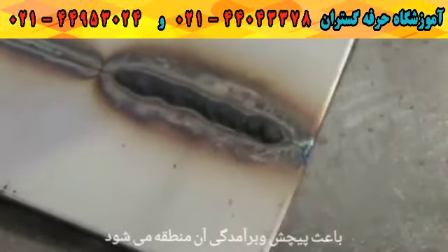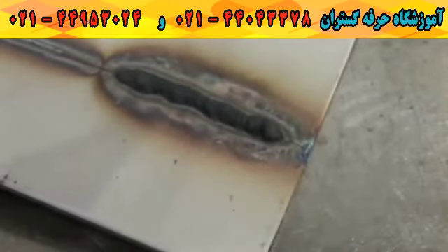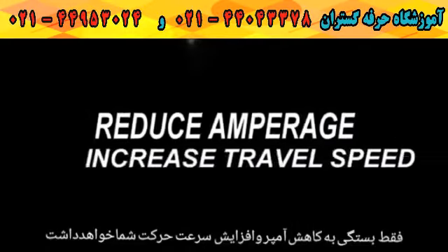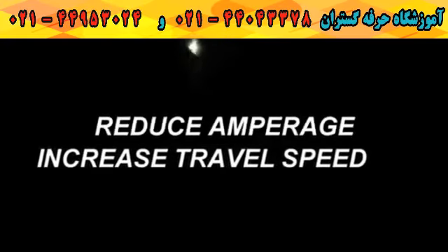Too much heat also has an effect on warpage. Stainless steel is unique in the sense that it doesn't transfer heat as quickly as other metals do. So again, too much heat in a localized area is going to make the material warp. How do we counteract that? It may sound simple, but simply reducing your amperage and increasing your travel speed will help decrease the amount of heat being applied to an area.